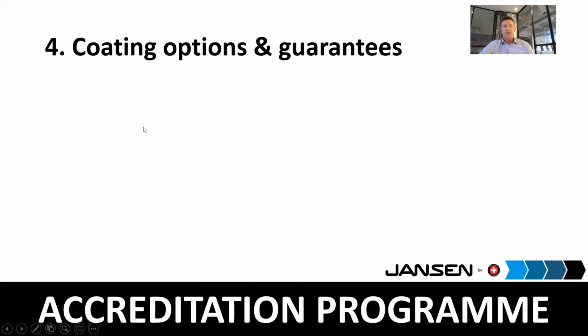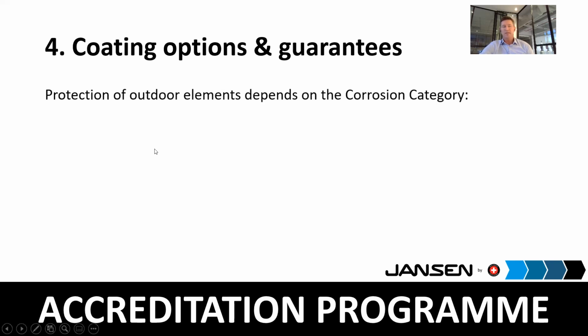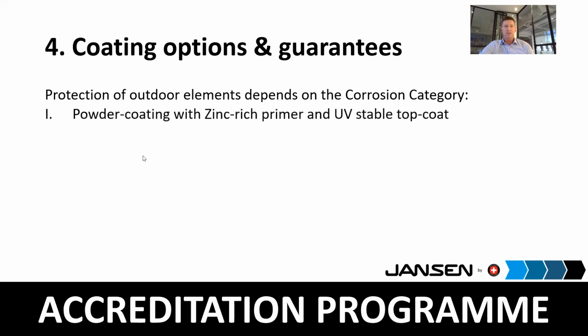Then the coating options and guarantees. The question you've been asking, what are we going to use? Now, for the protection of outdoor elements, it will obviously depend again on the corrosion category that we mentioned. But the first option would be powder coating with both a zinc-rich primer and a UV-stable top coat. And I think that's probably the simplest of the coating systems and possibly the most reliable in terms of your outcomes. Your powder coaters may not often use the zinc-rich primer, they might be using strontium primers, and in some environments that's fine.